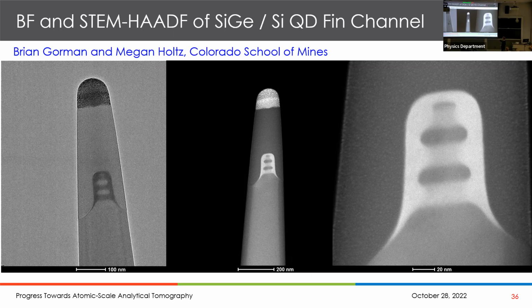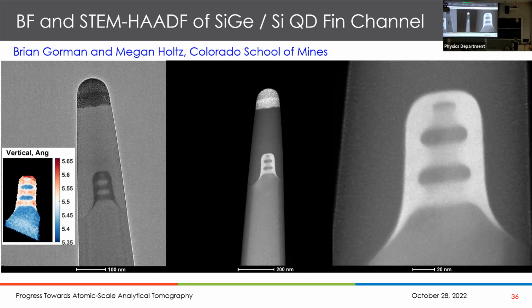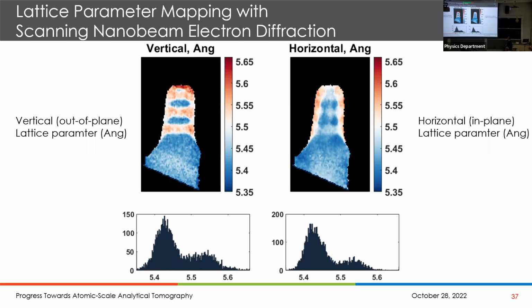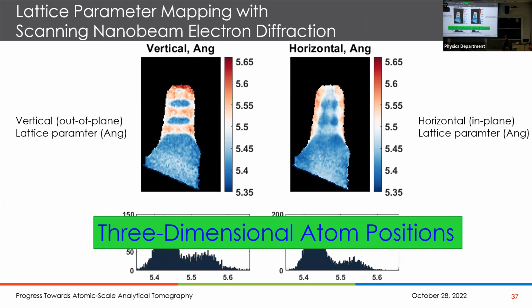Brian and Megan were looking at silicon germanium quantum dots in this kind of structure that's embedded in; they created an atom probe sample by FIB milling. Ignore this stuff up here, but you can see the quantum dots. And in fact, the 4D STEM results give you, and I'll show you this in the next slide, the displacement of the atoms away from, say, a nominal 5.5 angstrom. So this is a vertical displacement, this is horizontal displacement, and in that one area, you can see the distribution of atomic displacements relative to the ideal at 5.5 angstrom. In other words, this is giving really high precision, three-dimensional atom positions from the interior even of an atom probe specimen.